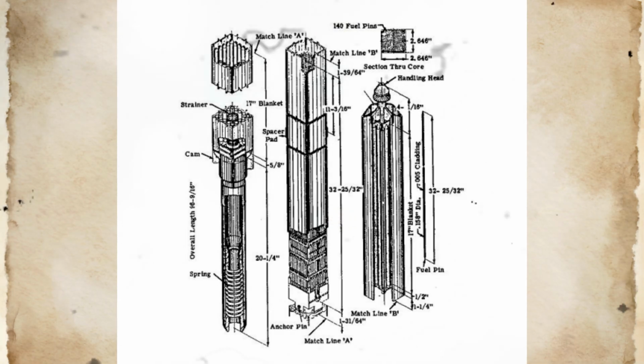The discovery of the loose zircaloy flow distribution plate in October 1967 provided definitive confirmation of the mechanical failure mechanism that had initiated the fuel damage sequence. The plate was found in the reactor vessel inlet plenum, positioned in a configuration consistent with partial flow blockage to the two fuel assemblies that had experienced thermal damage. Physical examination revealed that the plate had completely separated from its original mounting location and had been transported by coolant flow to a position where it could obstruct coolant inlet passages.